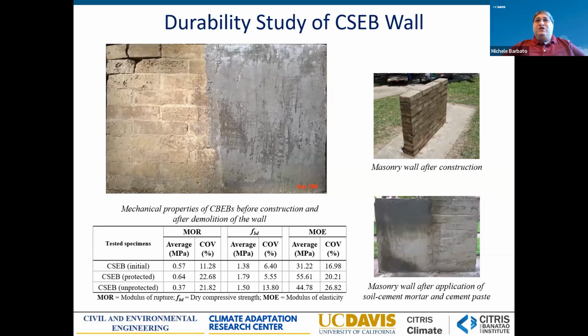And you can see in the unprotected side, very soon, this is a 6 months test during which we actually had two tropical storms. So it was short but pretty intense as a test. You can see on the side that is left unprotected, the mortar between the blocks is washed away by the heavy rain and wind, and this produces some mechanical damage to the bricks that are not anymore fully connected. On the other side, the one protected by our soil cement, let's call it stucco, although it's not a stucco, but protection, a layer of protection, we actually see no damage.